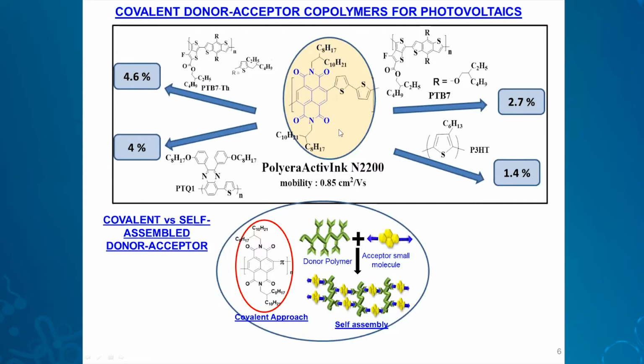But in these cases also, people soon realized that there are some issues. Because of the flat, highly aromatic nature of this molecule, it has a tendency to stack. And sometimes the stacking is not good for the device performance. This later leads to the development of crystalline phases in the active layer, which then leads to phase separation. So one important aspect when working with this type of polymer is to see what one can do to avoid this. In my research group, we have adopted a two-way approach: a covalent approach, where the donor and acceptor systems are covalently linked together like this, or a self-assembly approach, so as to avoid this pi stacking and to improve the electron transport in these materials.